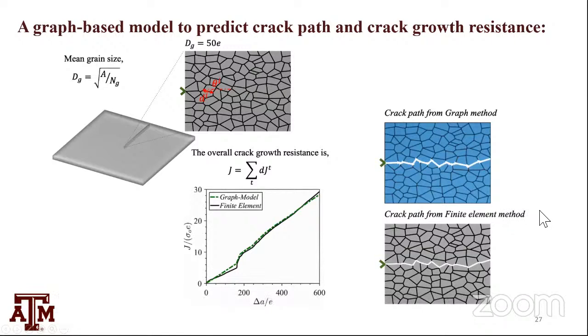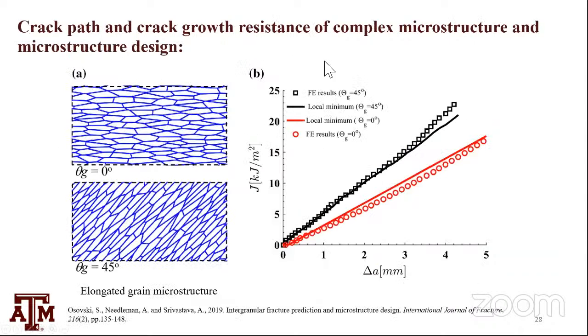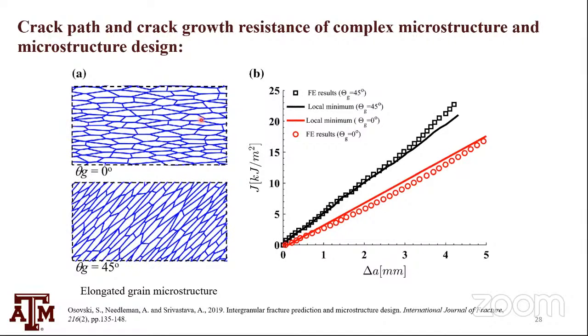So we already moved the algorithm beyond one thing at a time. I'm just showing more demonstrations. It's not only simple grains. We can have anisotropic grains, elongated grain microstructures, and we can still predict nicely. These are elongated grains. My crack started from here on this side, and in this one the crack is still here.